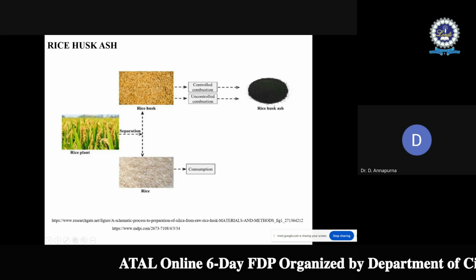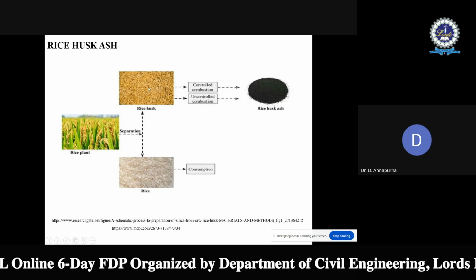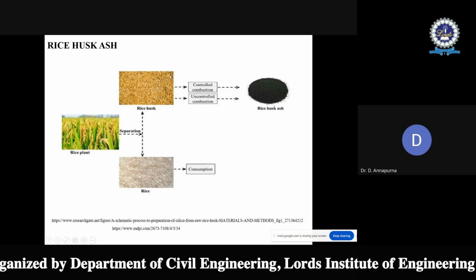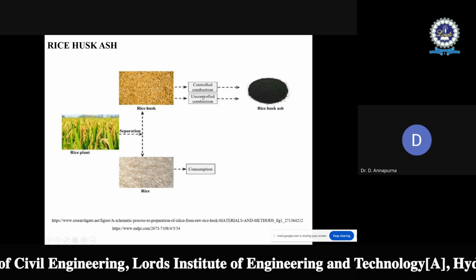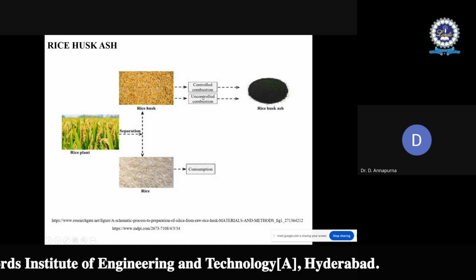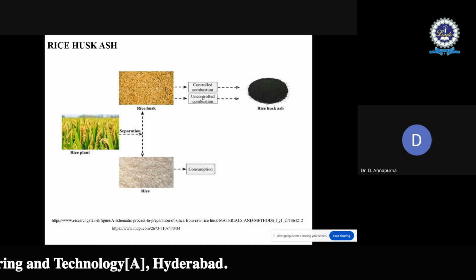And the next one will be agro-based material. This is rice husk ash from the rice plant. When the rice husk is separated from the rice, the husk should first be washed thoroughly. Then the dry rice husk should be kept in an oven at a temperature of 150 degrees Celsius.